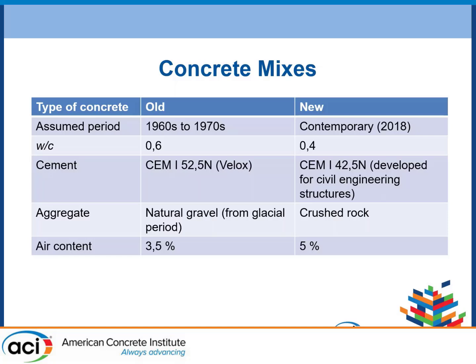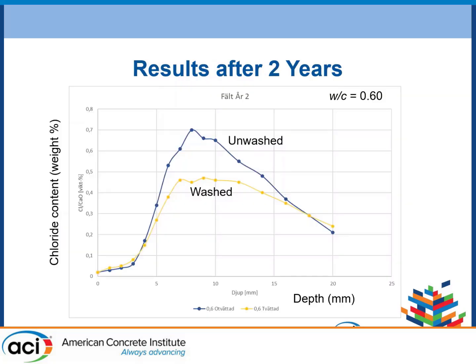And in the recommendation today, you should have a water-cement ratio not higher than 0.4. And in the old times, we used natural gravel from the glacial period, of which there are extensive resources, but it must not be used anymore. So today we are using crushed rock, which makes the concrete a little bit more complicated to place. And in old times, there was a recommendation of 3.5% of air. Today it is 5%.